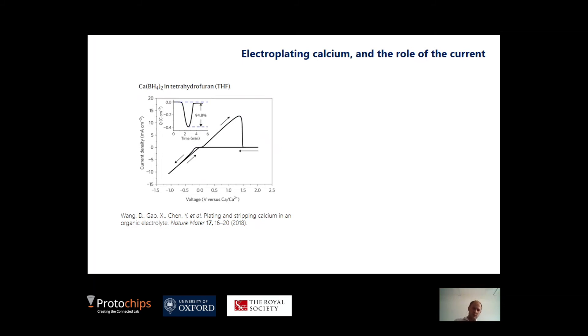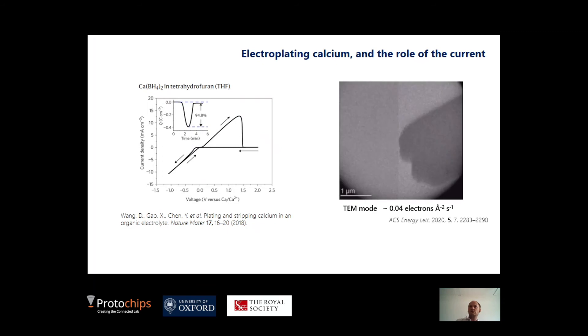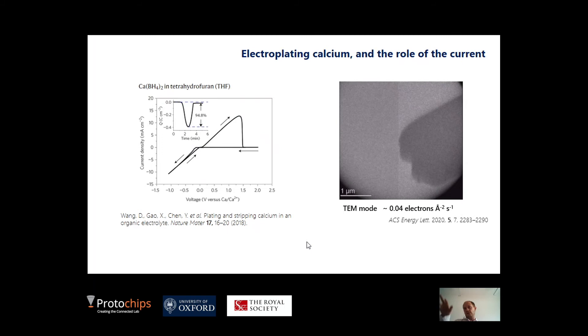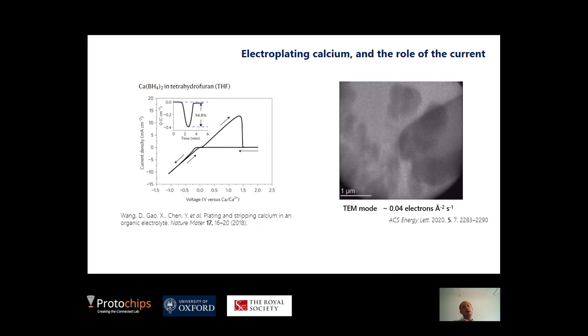From my point of view, I wanted to see if we could use the operando TEM to understand some of the morphologies that we saw during electroplating and stripping — or deposition, if you like — of this calcium metal, and see if it gave us any insights into the nature of the passivation layer and dynamics, and the trade-offs between that and the rate of deposition and stripping. There's a brief video here — what you'll see is on the right the platinum working electrode, and we just immediately see, as soon as you start plating, this dendritic growth of calcium shooting out.